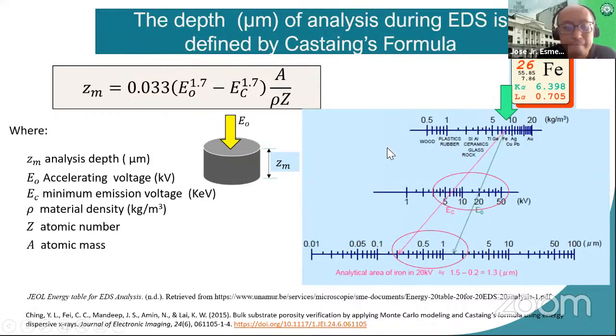Acceleration voltage, and also the EDS, energy dispersive spectrometer, also depends on the material density. This is called Castaing's formula. Let's say, for example, take iron. Iron has an ionization energy of about 6.39 kilo electron volts, and this is the density of iron. If we use an acceleration voltage of about 20 kilovolts, and this is the emission voltage of about 6.3, then we can see that the analytical depth is around 1 micron. So if you use a higher acceleration voltage, the analytical depth will become deeper. It depends on the density of your material.